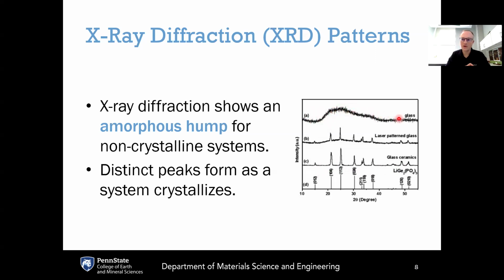So if you have a sample and you don't know if it is a non-crystalline material or a crystalline material, you can tell very easily by doing an X-ray diffraction experiment. If all you see is this so-called amorphous hump, then you know that it is a non-crystalline material. It could be either a glass or an amorphous solid. Or if you see all of these well-defined peaks, then you know that it is a crystal.